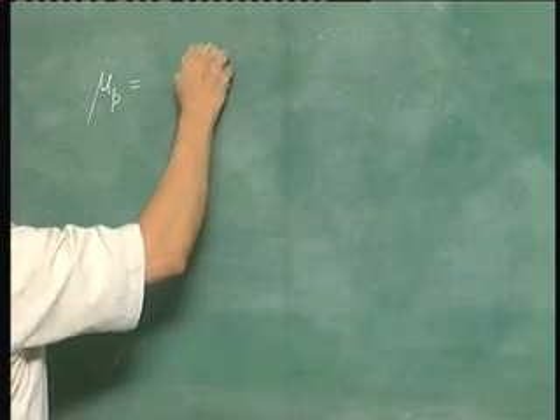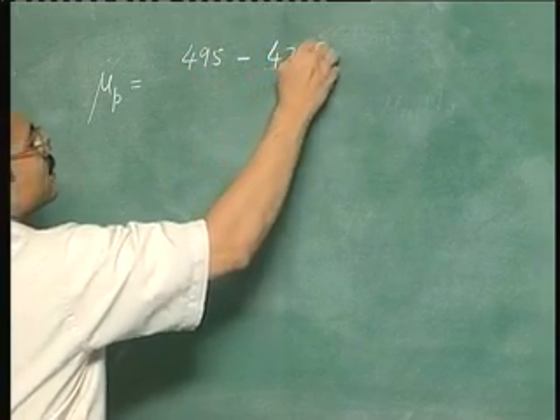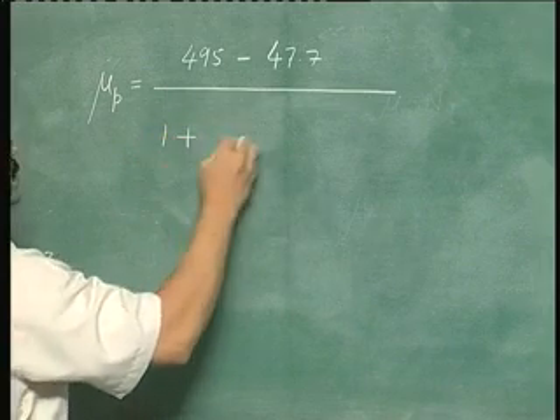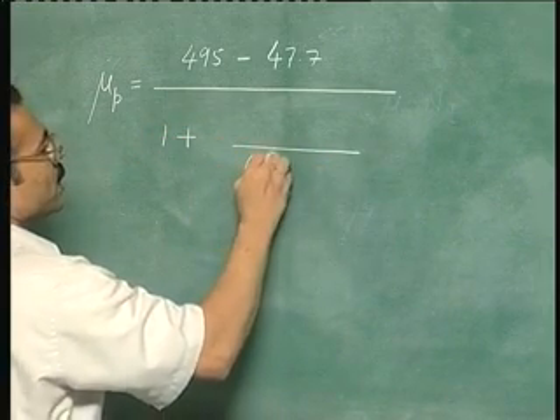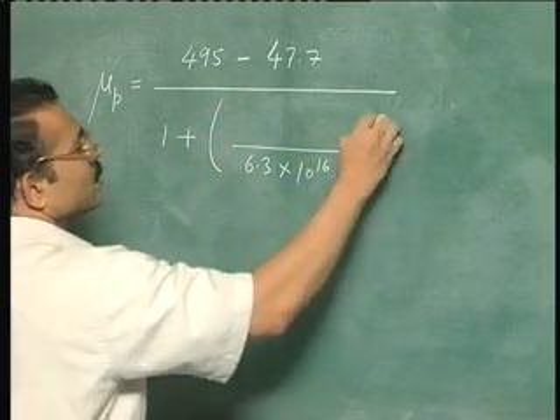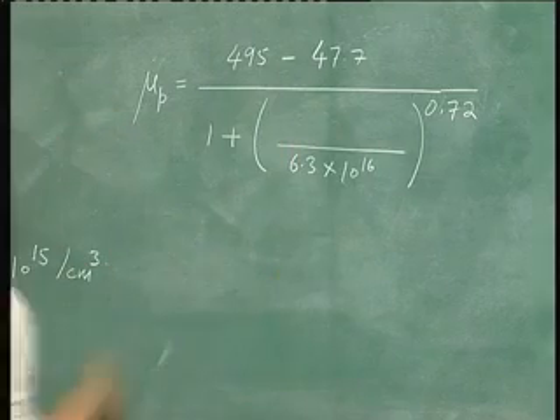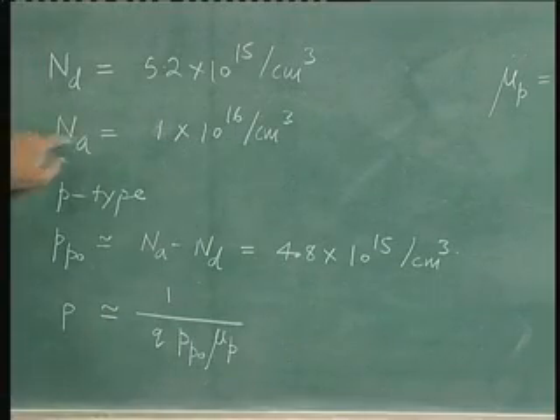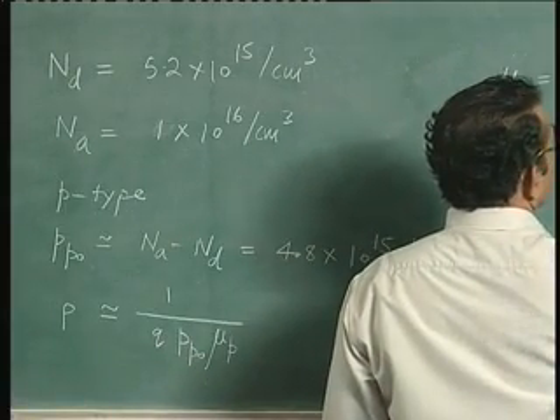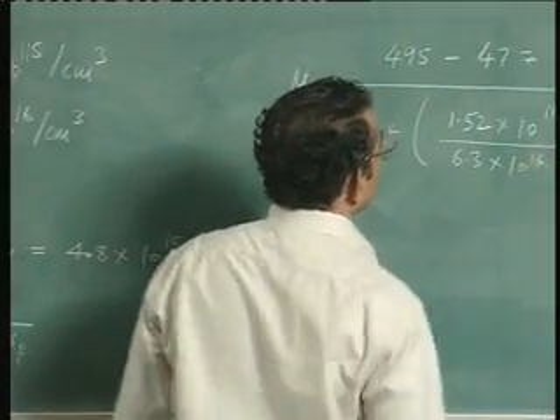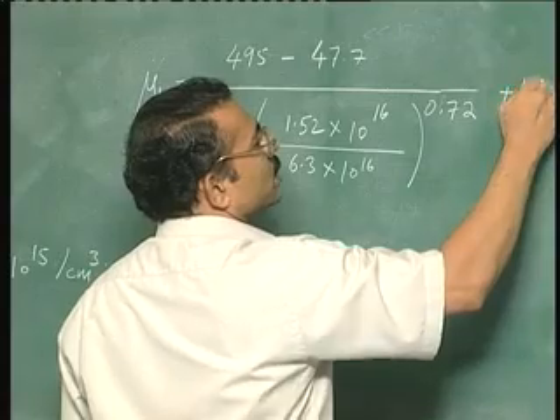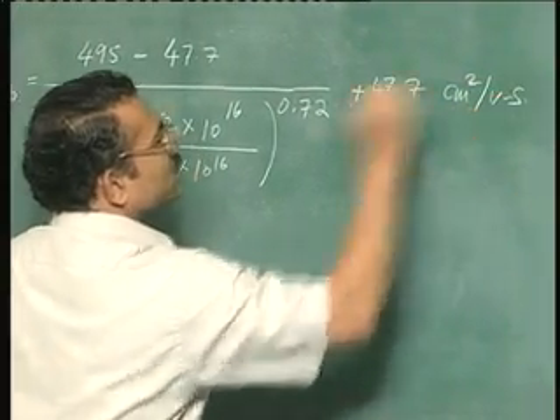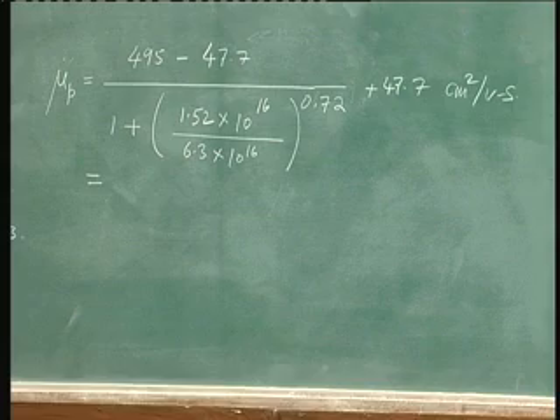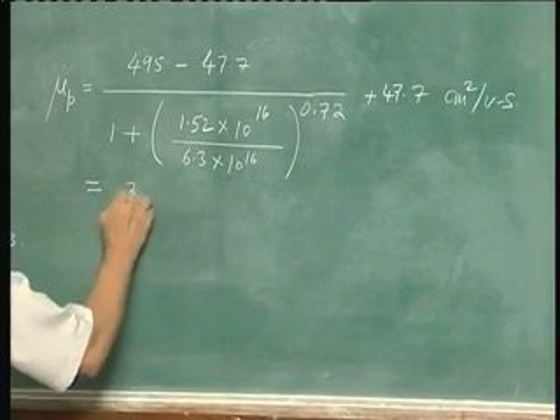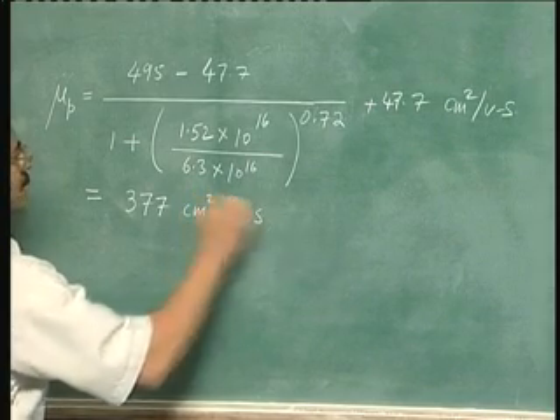So we use the formula mu p is equal to 495 minus 47.7 divided by 1 plus, now here 6.3 into 10 power 16 is in the denominator and power is 0.72. In the numerator we will have to put the sum of this Nd plus Na. So which is equal to 1.52 into 10 power 16, and plus 47.7 centimeter square per volt second. This is the whole mobility, and the result is 377 centimeter square per volt second. That is the whole mobility.